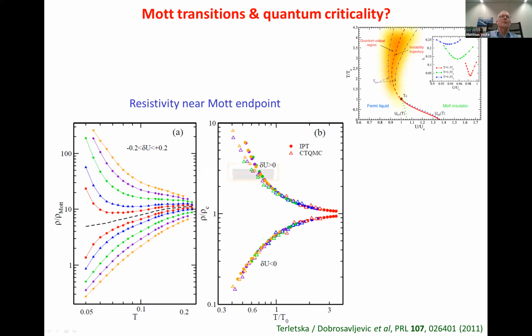Then you can do a scaling procedure which leads to a collapse of the data, as shown here in the center plot. This collapse is obtained by taking the absolute temperature over some reference temperature, and the resistivity relative to the resistivity on the red line. This is a scaling collapse characteristic of a quantum phase transition, because it's scaling where the absolute temperature enters. So this is clearly an indication—or let's say, this is conventionally taken as an indication—for quantum criticality.